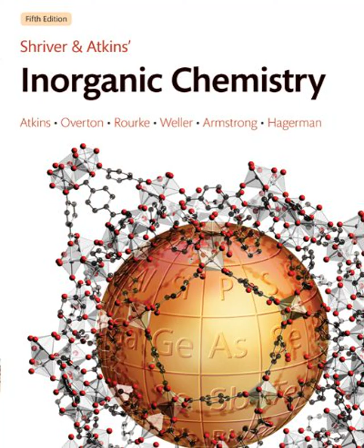Another is charge transfer. An electron jumps either between a metal and a ligand or from the valence band to the conduction band of the solid. Cadmium sulfide, CdS, is bright yellow due to this. Cadmium selenide, CdSe, is red. The band gap determines the color. You can also get intervalence charge transfer in mixed valence compounds like Prussian blue with both Fe2+ and Fe3+, where electron hopping between the different iron sites gives intense color, and sometimes it's trapped inorganic radicals like the S3 ion in ultramarine blue. And the non-colors, white and black.